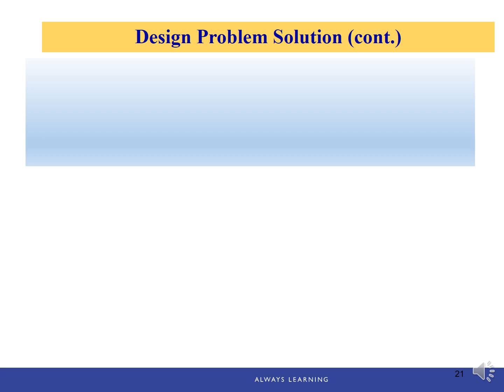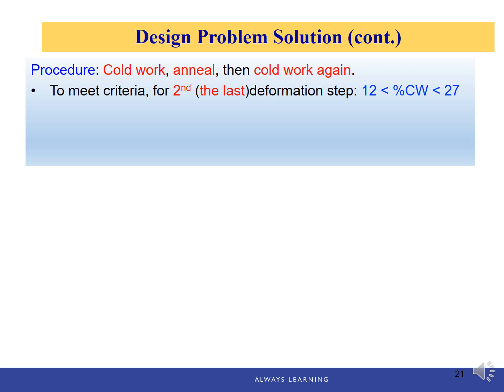Therefore, the procedure we're going to take will be: first cold work to an intermediate diameter and anneal to recover the ductility and the tensile strength. And then we perform cold work again. To meet the criteria, the second or last deformation step should be between 12 and 27% of cold work, mainly for the ductility to be retained. We can choose any value between those two values. So let's choose 20%. It's a whole number, which is easier for us to use in the calculation.